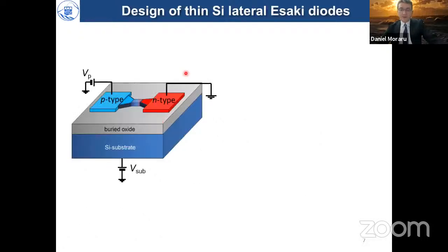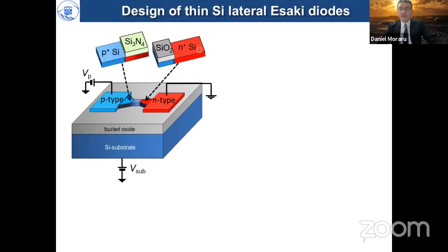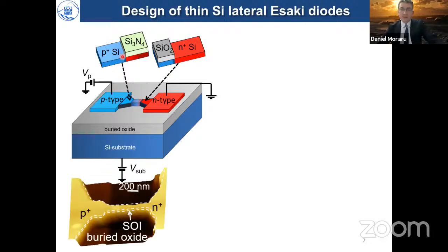So first of all, in order to access this kind of devices, this kind of scale, we fabricate silicon on insulator lateral Esaki diodes with a p-type region on the left and an n-type region on the right, and there is a buried oxide underneath. The silicon substrate can be used as a backgate. It's called here V sub, and this is the equivalent circuit that we are using. Typically, we use a silicon dioxide mask to dope N-type, and we use a silicon nitride mask to dope P-type. And this kind of technology, built up over several years in our clean room facility, allows us to fabricate p-n junctions in a very thin layer and also relatively narrow.